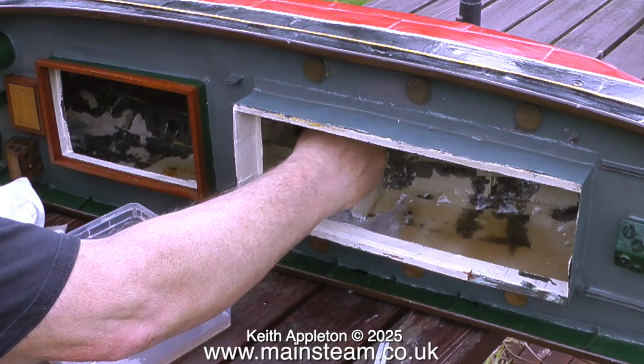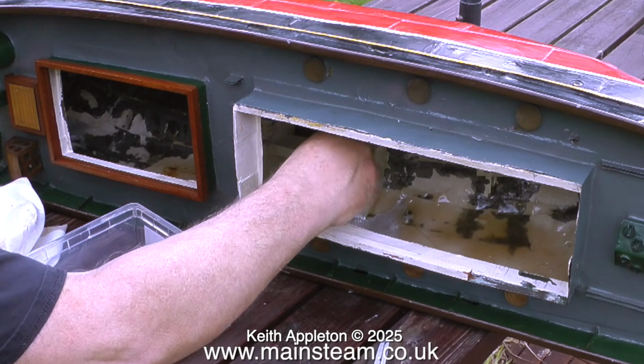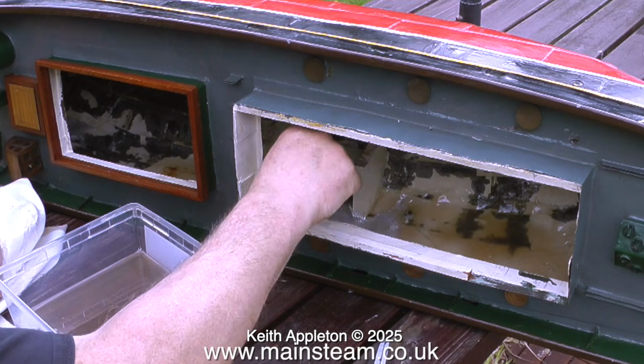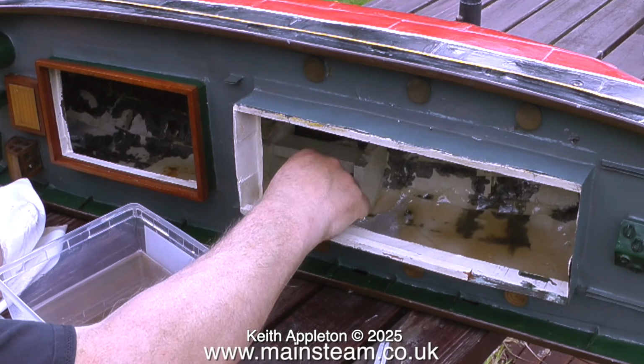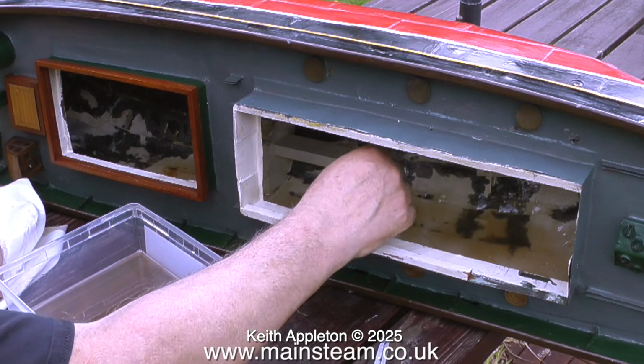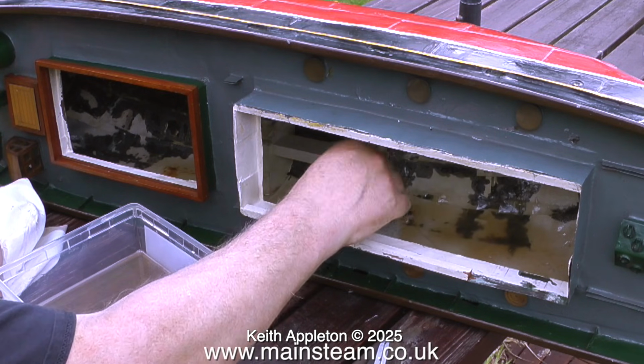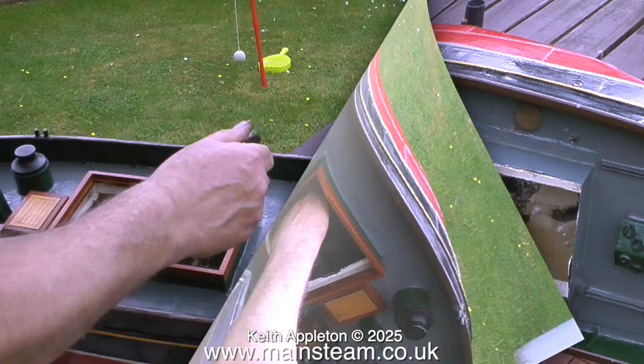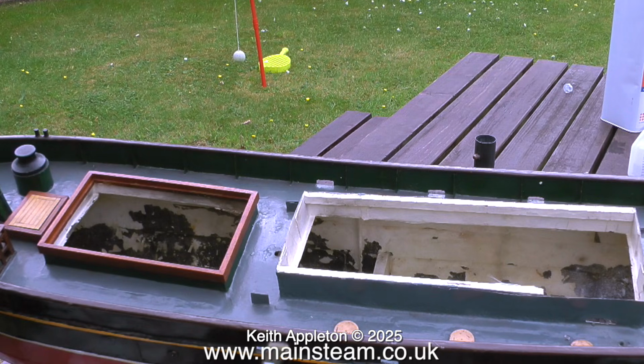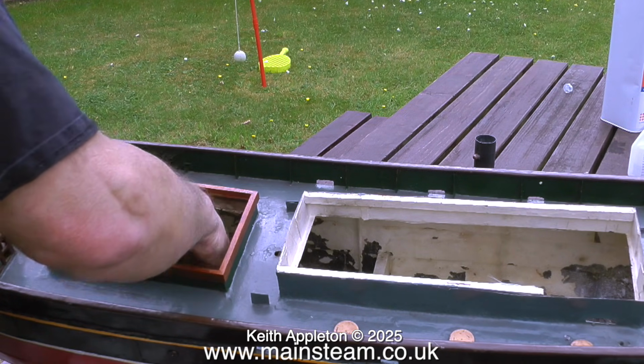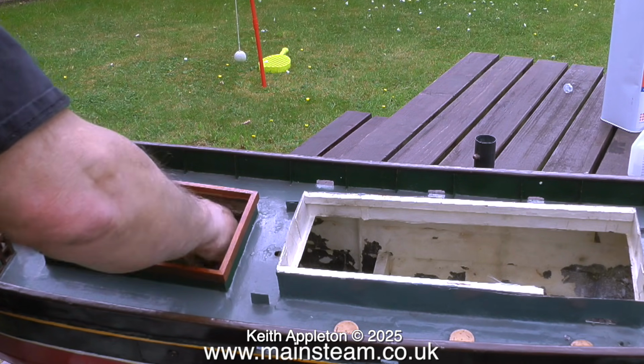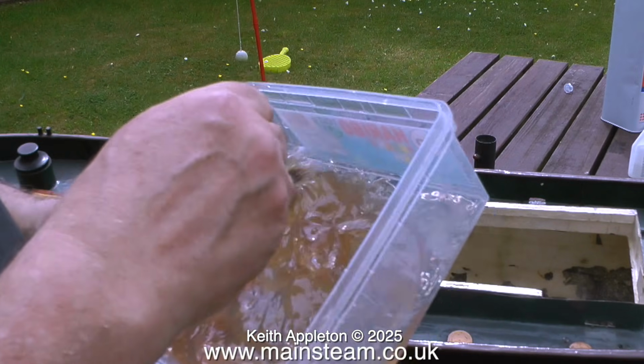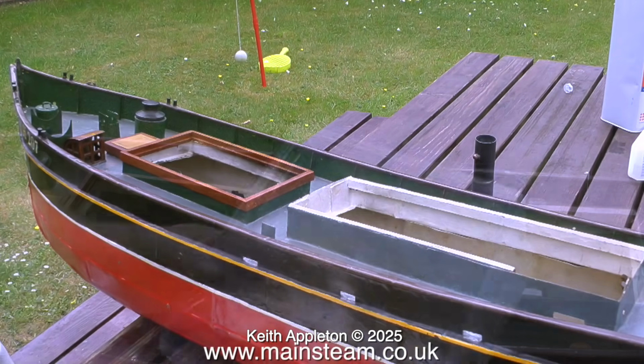I will be using some JB-Weld to repair part of it, but I don't think the heat generated by this polyester resin curing is going to affect the hull of this boat because it's made of metal plates that are soft soldered together. Here's a top tip. On a very hot day like today, don't mix too much of this resin because it will soon go off before you can get a chance to use it. I'll mix a bit less next time.